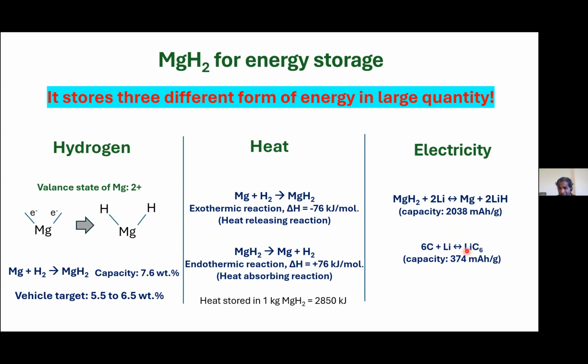Magnesium hydride in place of graphite can also react electrochemically with lithium and store several times higher quantity of electric energy. The reason is simple: here 6 carbon atoms are involved in the storage of 1 lithium. Here only 1 magnesium hydride is involved in the storage of 2 lithium. So from the lithium to active material ratio, you will understand why this capacity is very high. So it's a very interesting thing, all these things magnesium hydride does.